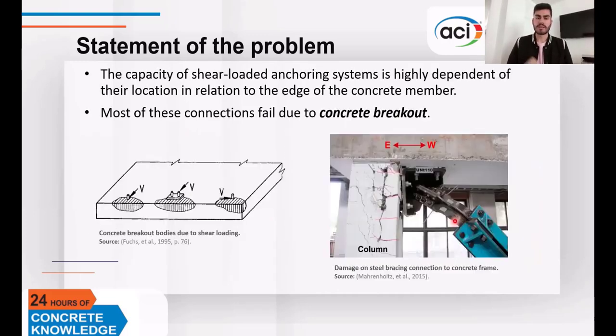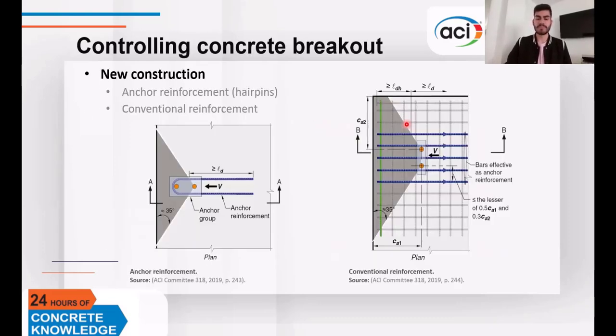balconies. Now, it may be somewhat intuitive, but the capacity of shear-loaded anchors is highly dependent on the distance between the anchoring system and the edge of the concrete member. Typically, failure occurs when the shear load generates such a displacement of the anchor that it induces a tensile stress within the concrete that exceeds its capacity, leading to cracking and the subsequent formation of a breakout cone. This failure mode is known as concrete breakout.